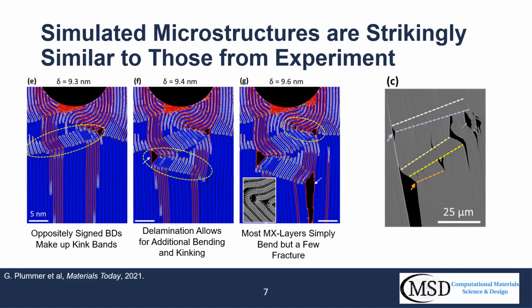The simulated microstructures are strikingly similar to experiments, with numerous delamination cracks and kink boundaries. Now, however, we can take a very close look at the steps which occur to produce this kinked microstructure. We see that when the layers beneath the indenter initially bend, a band of slip is nucleated, and slip calculations reveal that oppositely signed dislocation walls do indeed make up the kink band and its associated kink boundaries. The delamination cracks allow for many additional layer bending modes and the resulting complex kinked microstructure.